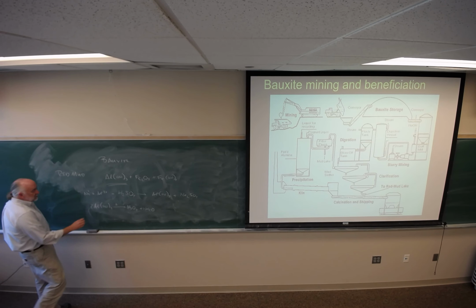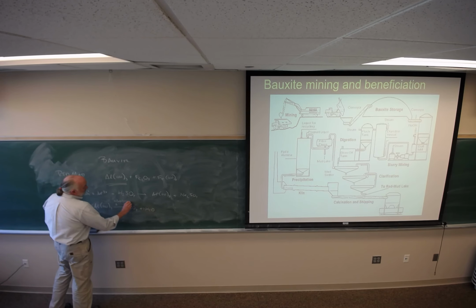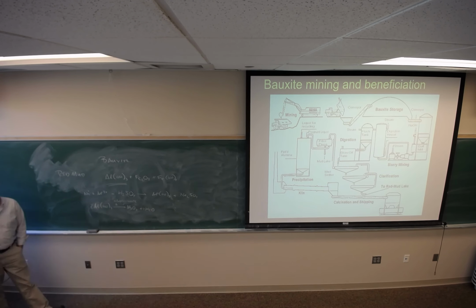This temperature is typically around 600 degrees C to 1,000 degrees C. And by the time you get to 1,000 degrees C, you have alpha alumina, which is what we most commonly know as alumina. If you're at lower temperatures than that, there's a whole series of different aluminas you can form: gamma alumina, delta alumina, etc. Okay? So you form aluminum oxide. The largest use of aluminum oxide is to then go to what's called a Hall-Héroult cell, where you do an electrolysis reduction to extract the aluminum, or remove the oxygens, to end up with aluminum metal. Okay, so that's where most of it goes.